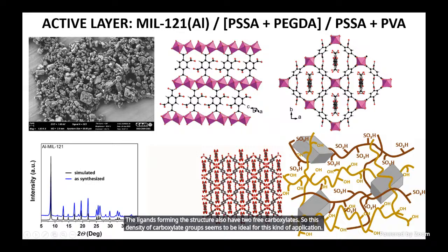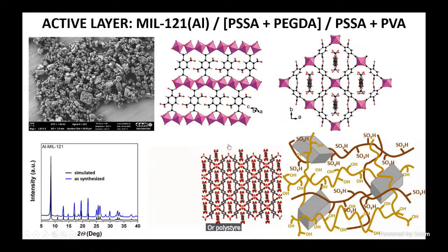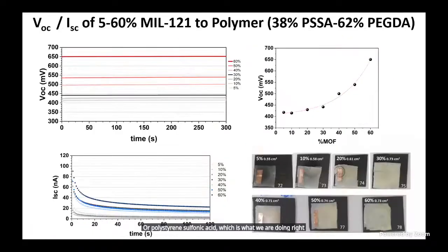But of course, this is a powder material, and you need to structure it. So you need to combine it with the typical materials that have been used for moisture electricity generators, which are PVA or polystyrene sulfonic acid, which is what we are doing right now. We're exploring these materials. We also added some polyethylene glycol diacrylate, and what we see in this slide is that the hypothesis is confirmed. The more metal organic framework loading we add into this system, the higher the open circuit voltage we can generate. Here we can obtain 650 millivolts.